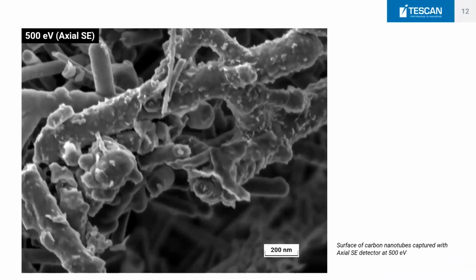So this is the image which you get from the secondary electrons. It's a surface of carbon nanotubes, acquired at low accelerating voltages, and you can see all the tiny details on the surface. So these kinds of nanotubes are usually put in different composites in our case, right? We put them in and we believe that they enhance a lot of properties. So when we speak about characterization, it's important that we see what the structure is, how long they are, how wide they are, what the surface is, and whether it adheres well with the composite.